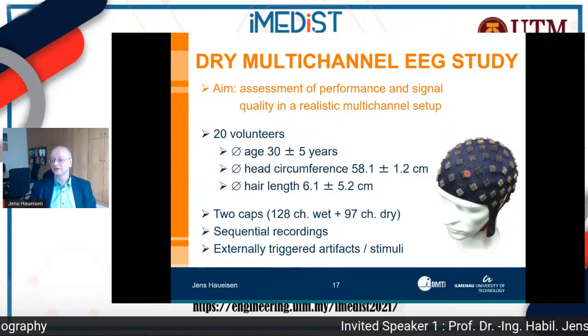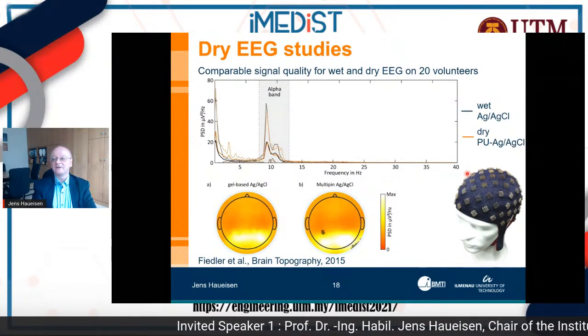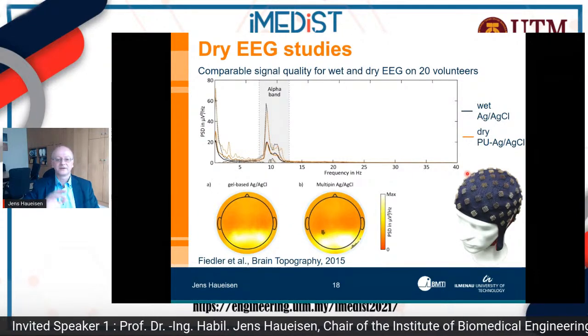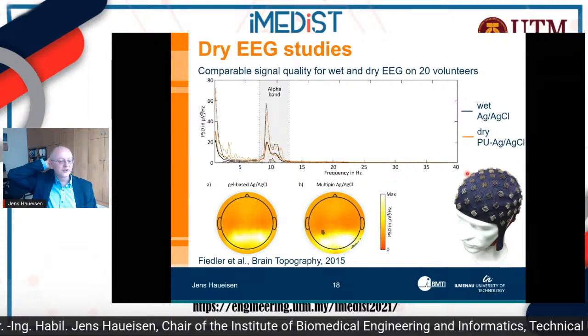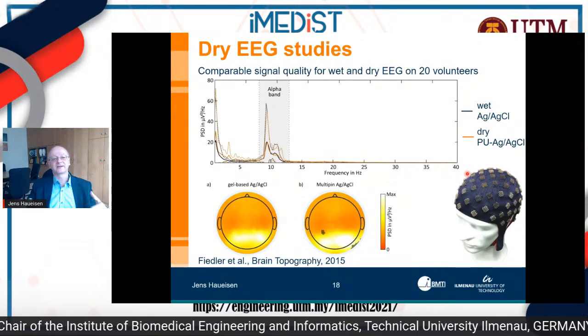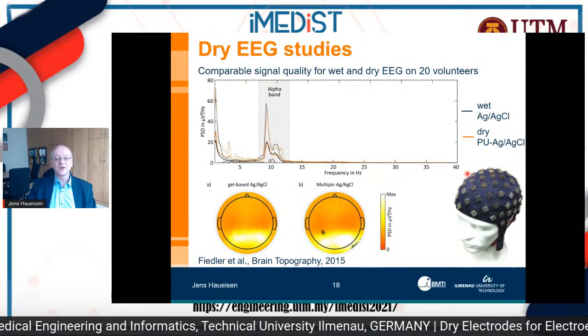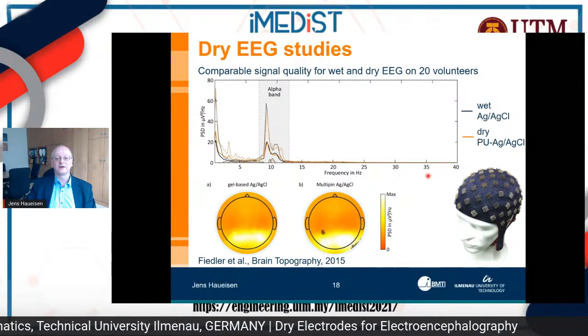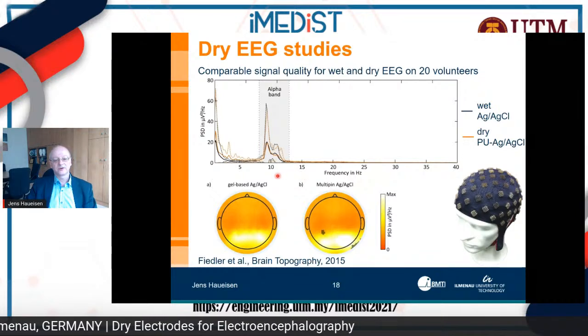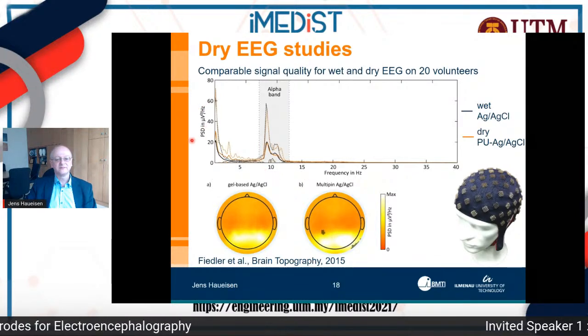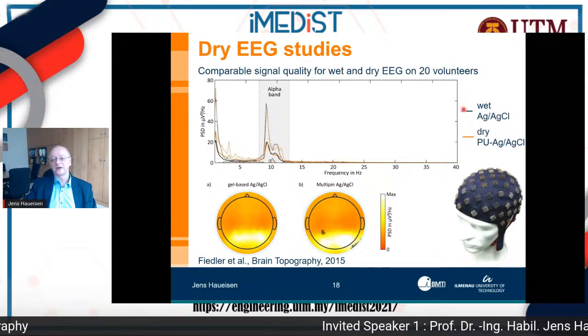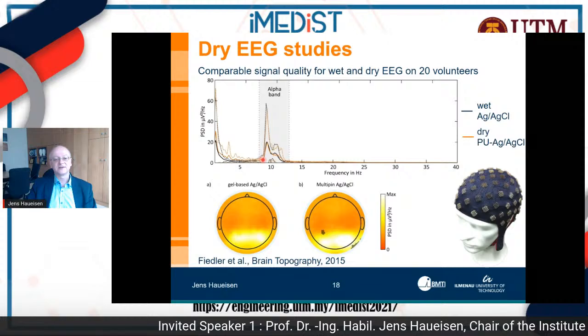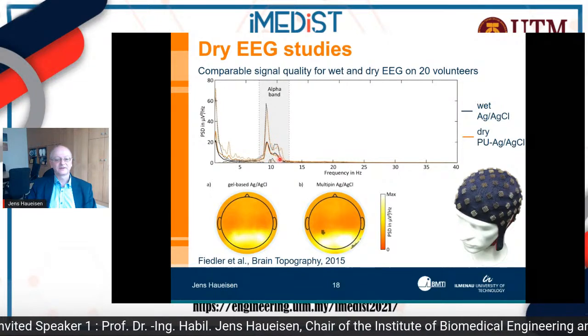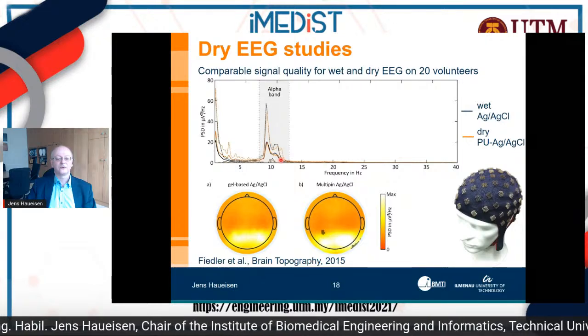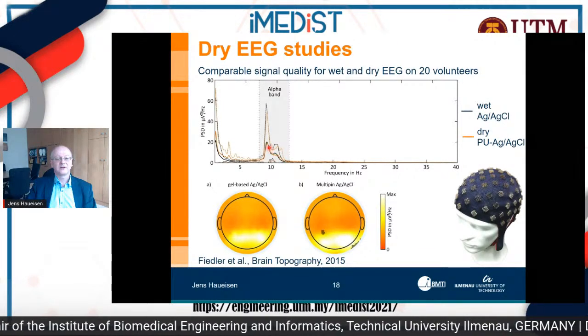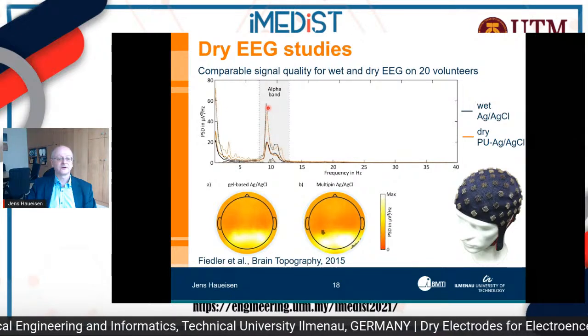Now what comes out is the following. So we have here, for example, the alpha activity. The alpha activity is the activity which you measure typically over the occipital cortex, and it is related to a relaxed and eye-closed state. It is the strongest activity actually in the brain in the ongoing EEG. And what you can see here is the power spectral density for the dry in orange and the wet in blue. And what you can see is that we have here a nice alignment of the peaks. And this is already the grand average of all the 20 participants. And you also see that the standard deviations are nicely aligning.